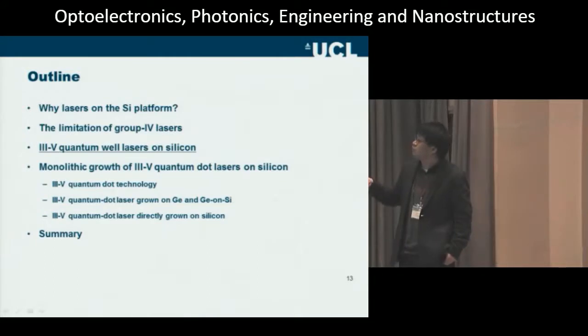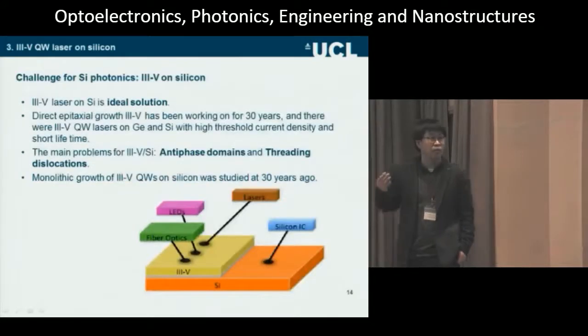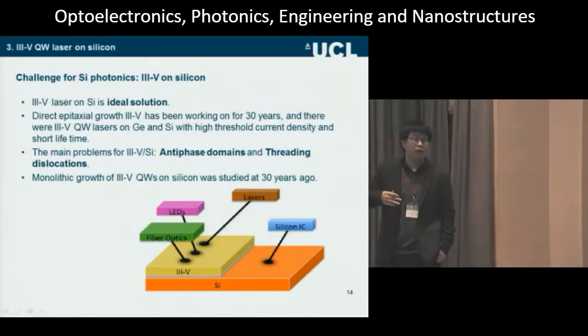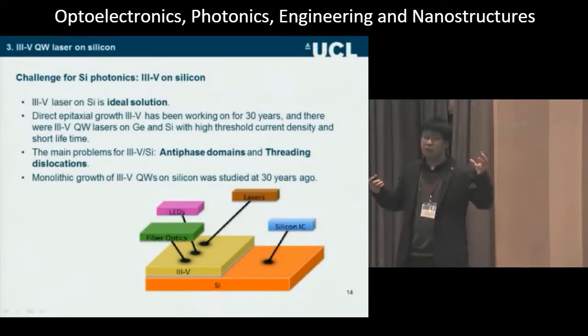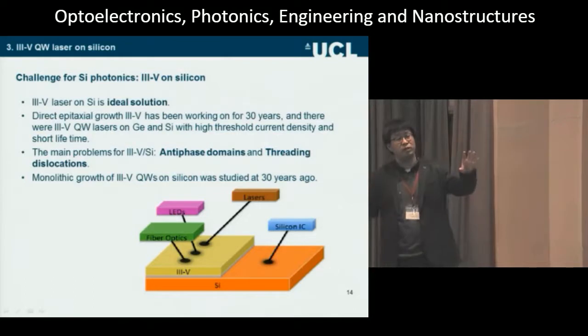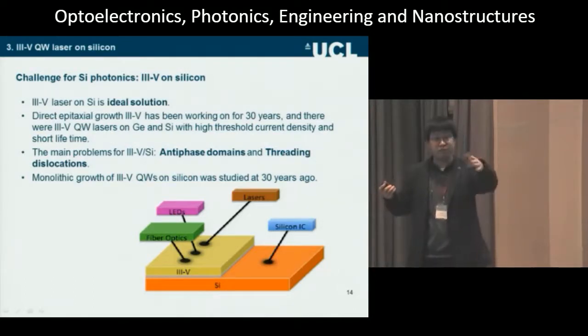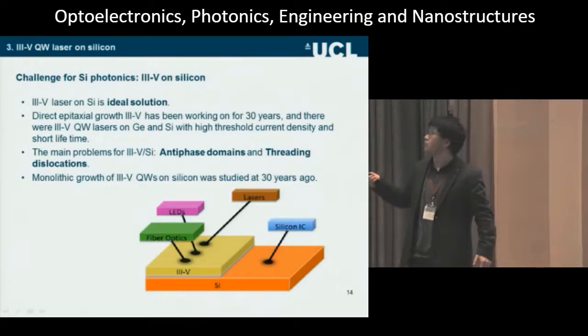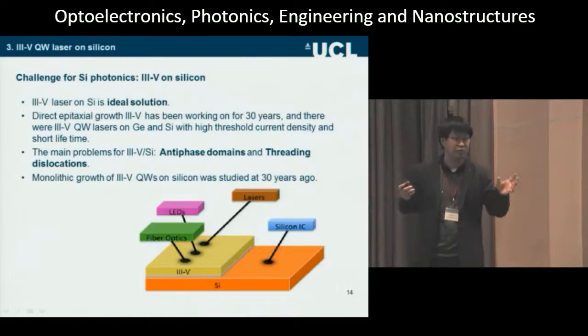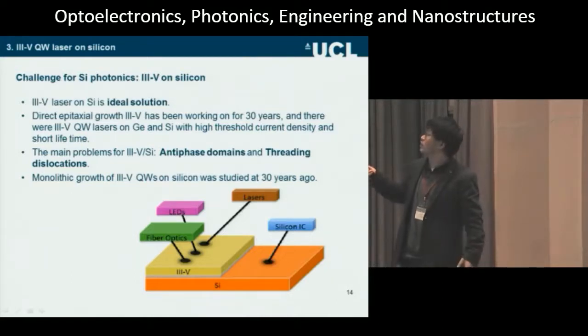So what happens with group 3-5 materials? Because of the challenge of group 4 laser, it's a very good idea to put a 3-5 laser on silicon. Because 3-5 laser has high speed and a lot of different wavelengths. But what's the main problem? If you grow 3-5 material on silicon, you will form 2 types of defects. One is that you grow polar materials on a non-polar substrate. So the first layer is very important, and you have a phase problem. The other one is the mismatch. The lattice constant between silicon and the majority of group 3-5 materials is different, so you will have threading dislocations.